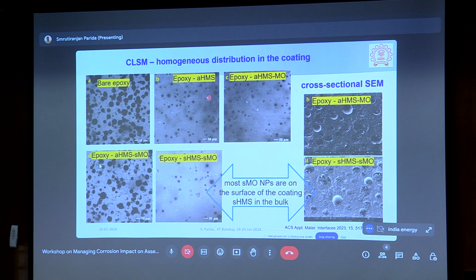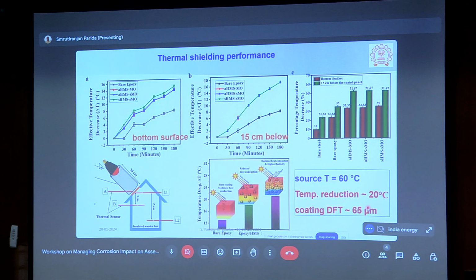And then if we add MO, there is a slight increase in the density, but still, because MO doesn't give any scattering in the image, we only see the hollow microspheres. And then, if we modify both the hollow microsphere and the metal oxide and add them to the coating, we can see a big decrease in the density on the surface. We do not see a lot of hollow microspheres on the surface here. At the same time, in the cross-section SEM, most of them are distributed throughout the coating, but not on the surface. The density at the surface is less, and this is being replaced by the metal oxide on the surface. Therefore, we get a coating in which the metal oxide is right at the top, and everywhere else the hollow microsphere is distributed all around it. So the composite effect of that is very, very profound.